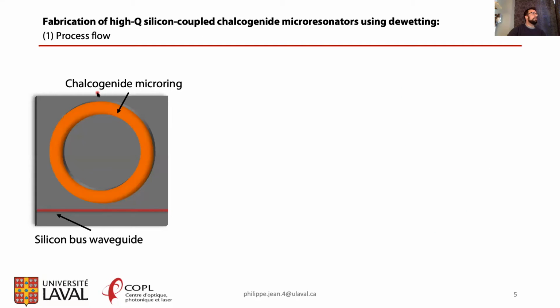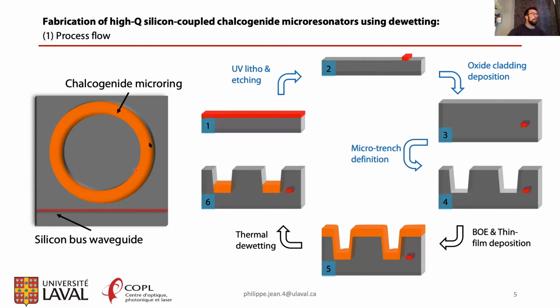The fabrication approach we chose is a relatively simple one, in that we basically only dry etch microtrench waveguides to form the microresonators directly inside the silica cladding. Then these microresonators can be aligned next to the silicon waveguide for evanescent coupling. Here you can see an overview of the process flow. The first 4 steps are done in foundry, in this case by AMF. The last 2 steps are done at COPL, and they consist of a thin film deposition as well as a thermal dewetting step.